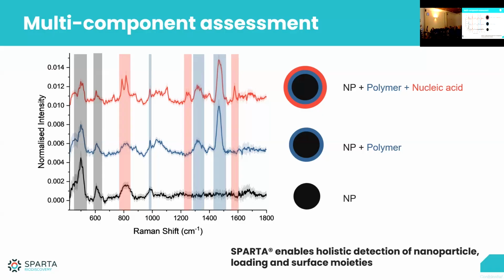We have a database. It's very widely used. And even with Raman imaging techniques, for instance, that are not SPARTA, the positions of where these peaks are, for instance for nucleic acid, will be the same because it's calibrated. So we always know that around 780 or so is a key peak for nucleic acid. That's not going to change, but it's much nicer to see the control, of course, with the absence and the presence of the sample.